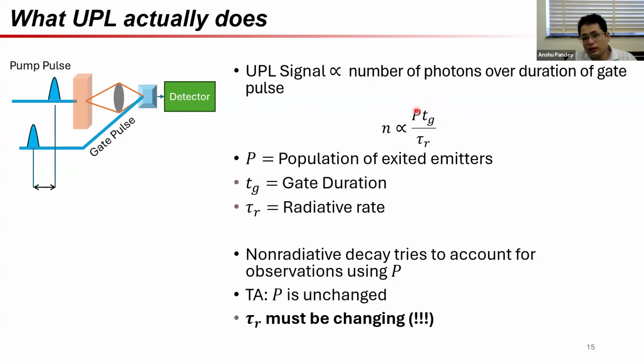So what is this determined by? We can just simply think of it as a proportionality problem. We know that it will depend on how much of the sample is excited. So this is P, the population of excited state emitters. What else will determine it? It will be determined to good measure by how long this gate duration is. This is TG. And it will be determined, of course, by the radiative rate because of the sample.